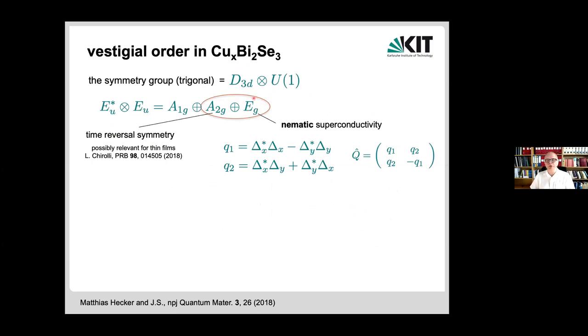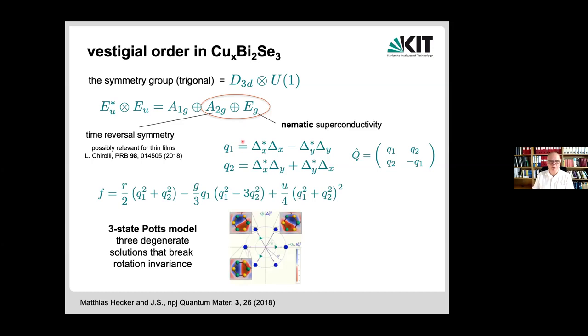It's a two-dimensional representation in its own way, where you have two non-trivially transforming composites that you can form and that you can build into a traceless symmetric tensor, which is what you need if you want a two-dimensional nematic. If you expand the entire collective field theory for those degrees of freedom, what you find after a little bit of calculation, from the microscopic on, is that the continuum field theory for this problem is that of a three-state Potts model, which is what you probably would be expecting if you look at these three pictures here. So we have a three-state Potts model that in three dimensions would have a first-order transition, in two dimensions, second-order. Maybe this order could also drive this first-order transition, second-order. But we have a three-state Potts model transition as a potential composite order that could occur.